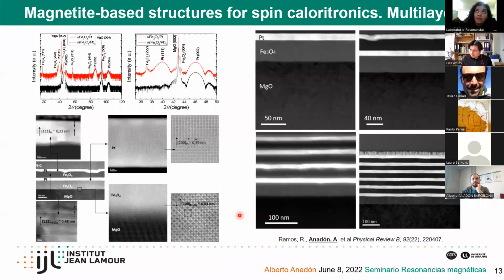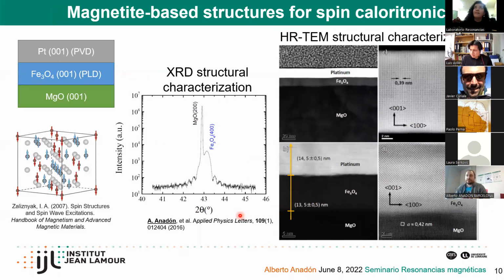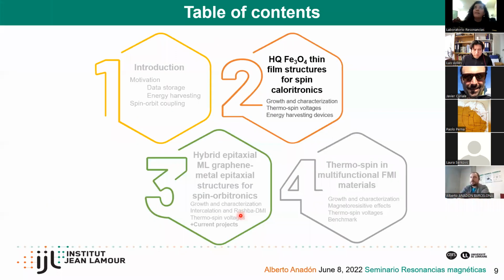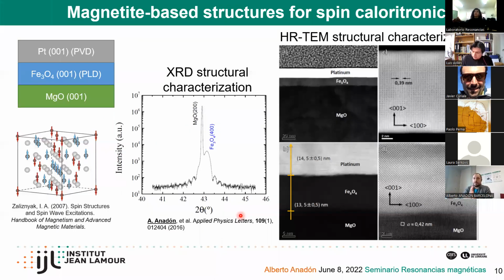You can tune this by the growth properties, as you probably know. We have done some studies in maghemite, and I think that the spin-Seebeck is in the same order of magnitude. The difference is maghemite is completely insulating, while magnetite is a bad conductor. So in this case, you also have the Nernst effect. Probably this will increase the total signal that you have. I cannot remember exactly, but if you want, I can send you some references. I think that our conclusion was that in maghemite the spin current generation was more or less similar to that in magnetite. Thank you.